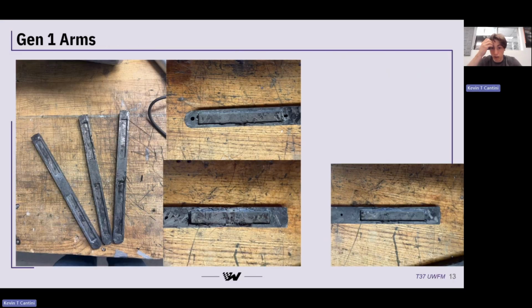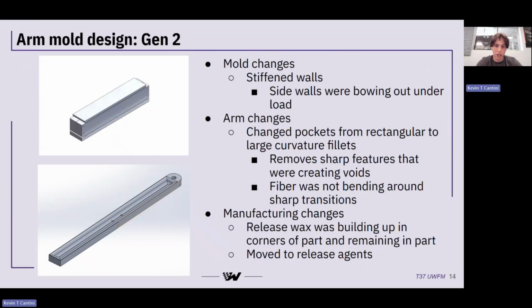Here are Generation 1 arms. You can see the problems, voids, and a rough surface finish, concentrated around those sharp corners on the pockets. The fibers couldn't bend around those sharp transitions very easily, so void-prone regions formed exactly where we didn't want them to. Right around those sharp corners, all of those will be load-bearing.